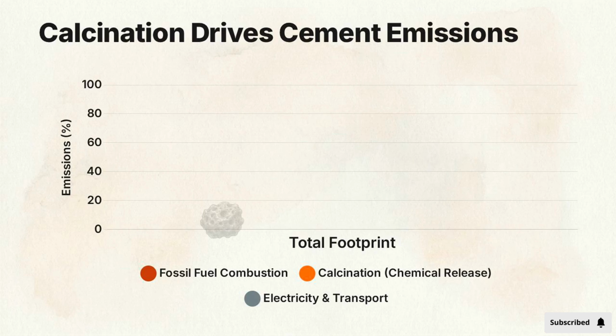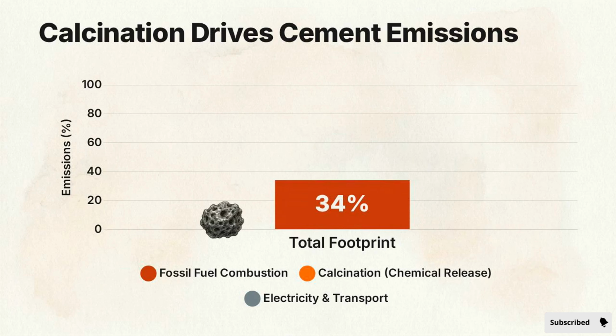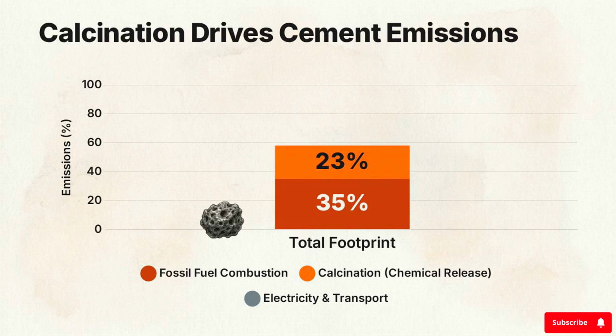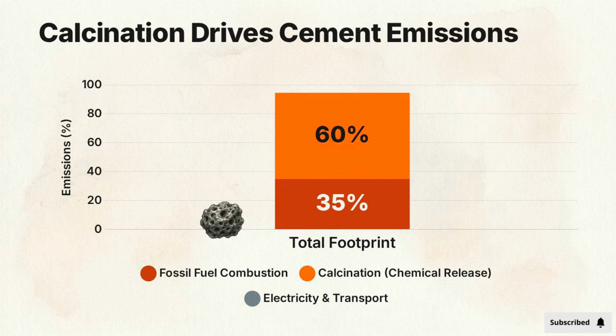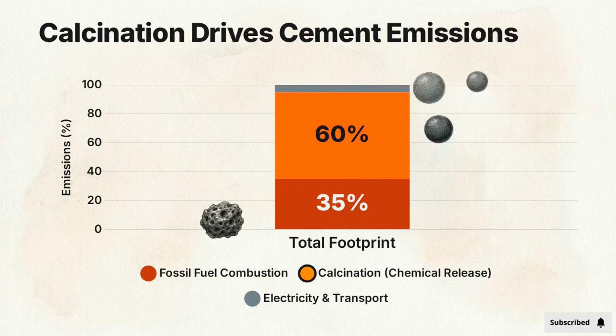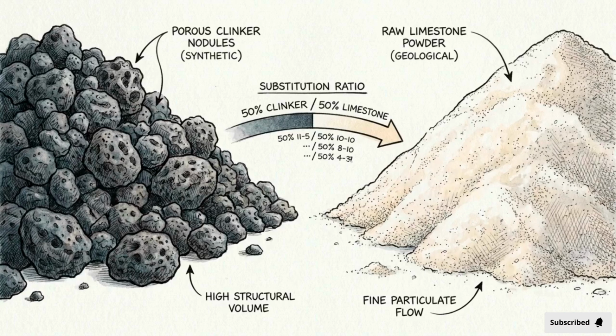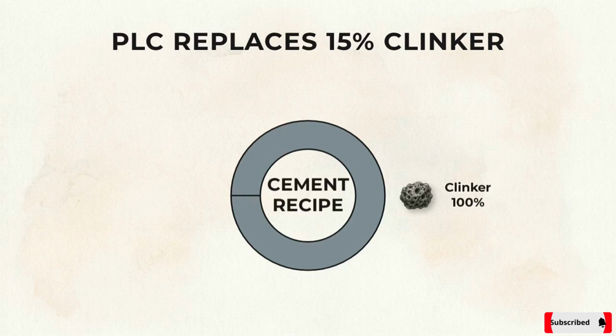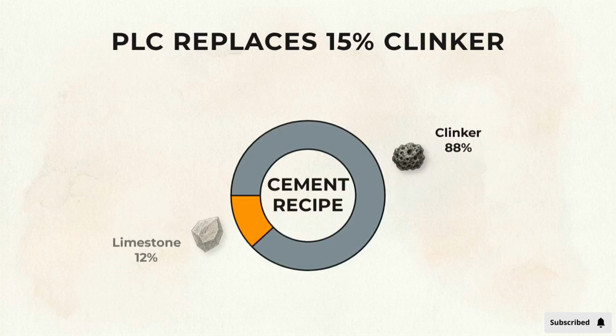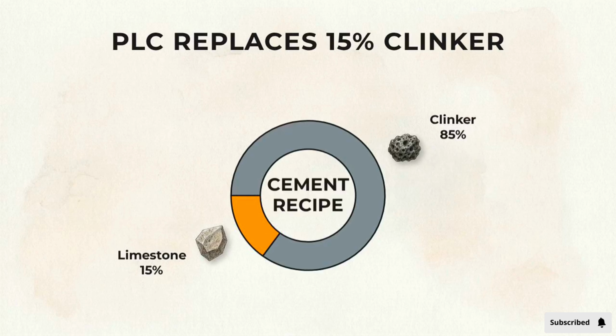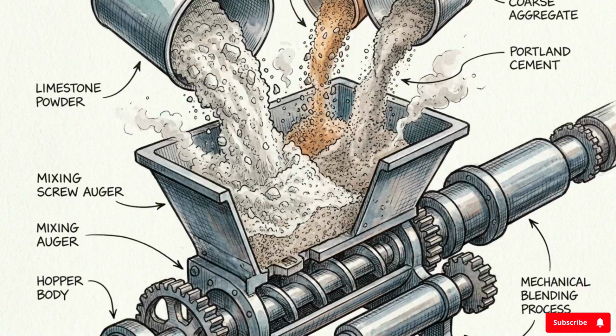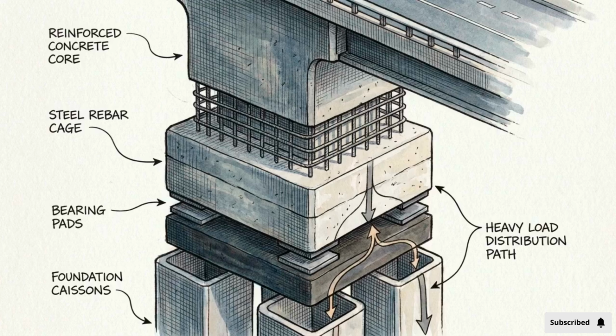This chart shows the emissions challenge. Roughly 35% of a plant's footprint comes from burning fossil fuels, but 60% is caused by the unavoidable chemical release that happens during calcination. To address this, the industry is pivoting toward a new standard, Portland limestone cement, or PLC. PLC replaces up to 15% of the energy-intensive clinker with raw, unburnt limestone powder. By skipping the kiln for that portion of the recipe, the carbon footprint drops by 10% without sacrificing structural strength.